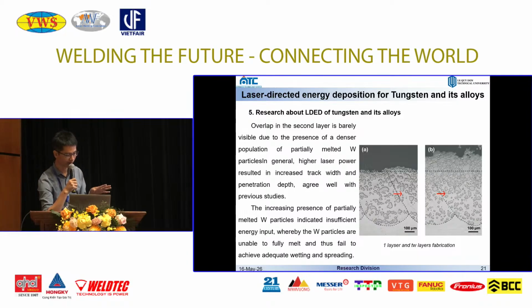And we also make a very thin layer, only a single layer and two layers of the material on the same substrate, and we can see that the tungsten particles can be partially melted into the substrate. Something we can notice is that for the single layer the surface is pretty smooth, but from the second layer upward the surface becomes unstable. This is maybe caused by insufficient energy input, whereby the tungsten particles are unable to fully melt. It is kind of difficult to achieve good wetting and spreading of the material.